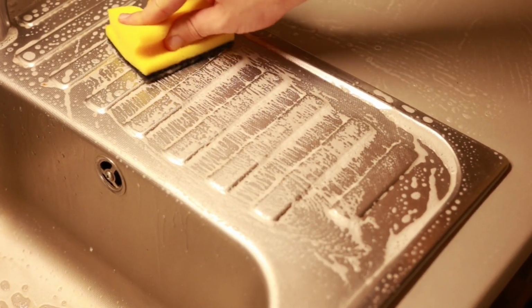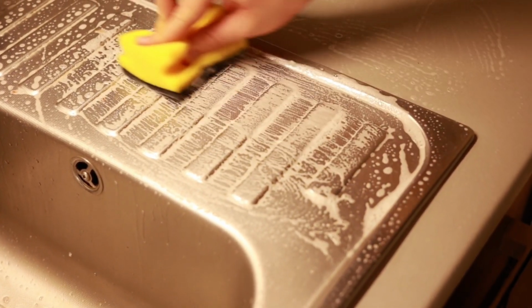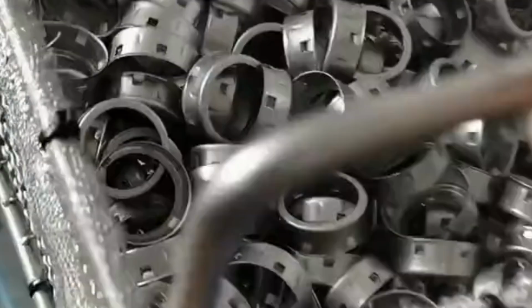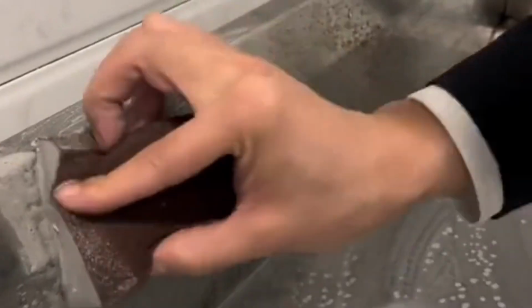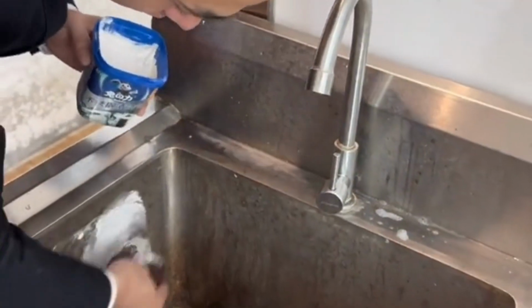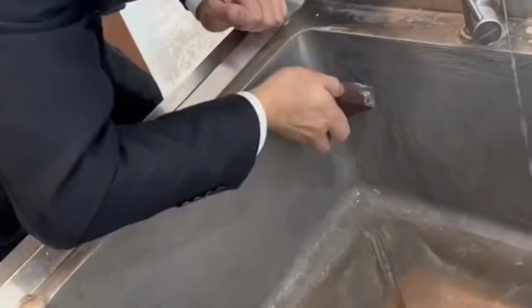Of course, correct design, processing, and maintenance are also crucial. For example, avoid water accumulation in dead angles by designing drainage holes. Avoid cross-contamination with carbon steel during processing, and regularly clean with warm water and a neutral detergent. If rust spots are already found, you can generally treat them with stainless steel specific rust remover, 3M polishing cloth, or a home remedy of white vinegar and baking soda.